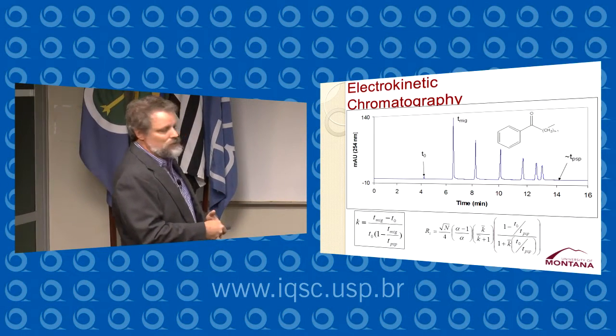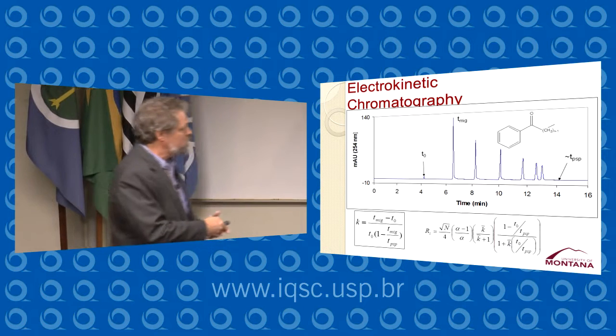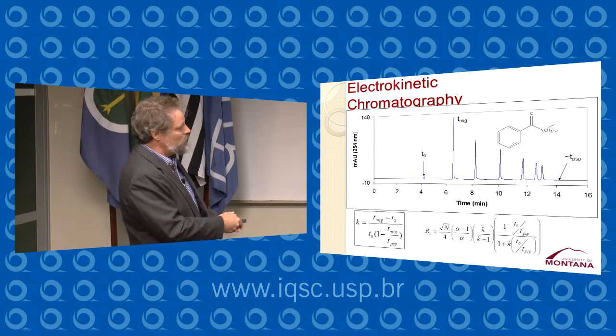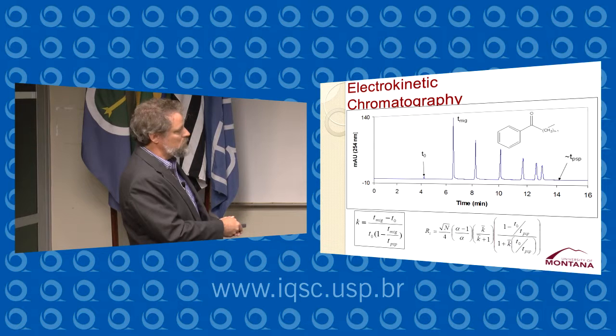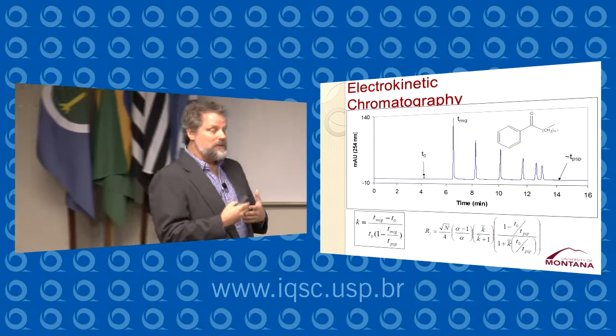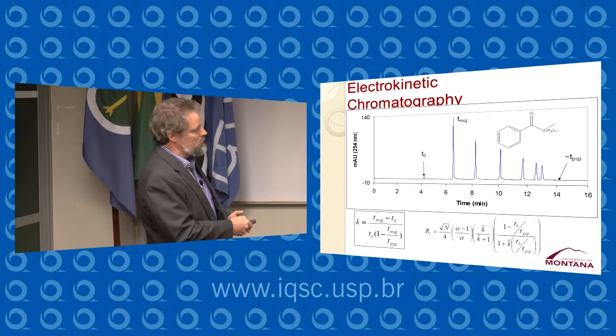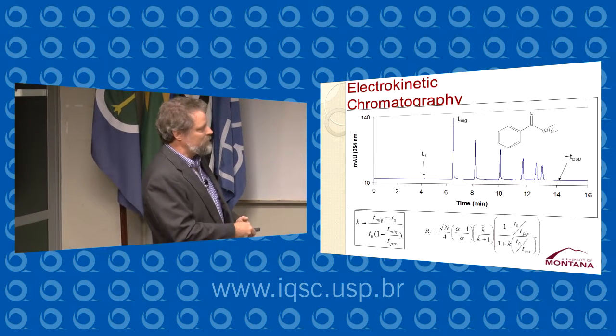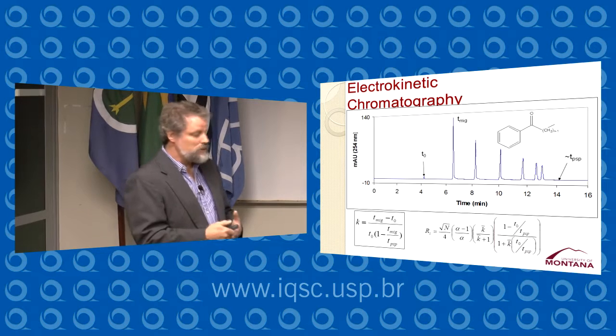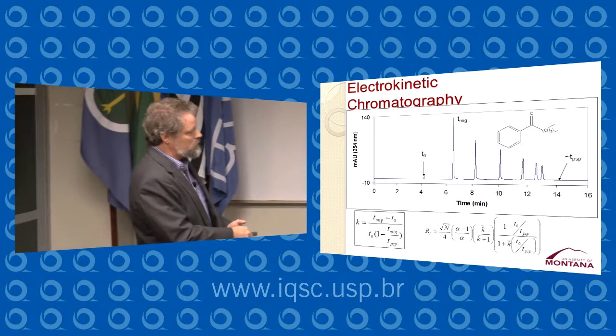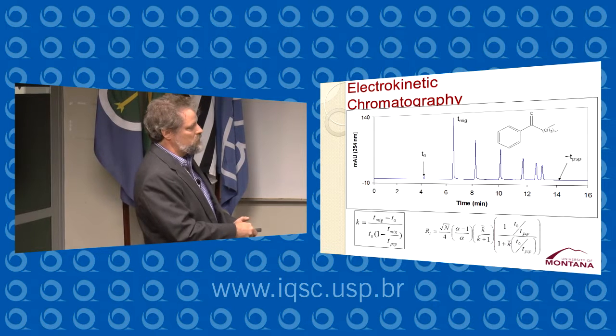So that's a significant difference between electrokinetic chromatography and conventional chromatography. We have this separation window to work with. We can calculate retention factors just like we do with conventional chromatography, but now there's a new term in the equation which accounts for the migration time of the pseudostationary phase. And we can also predict what we would expect to get for the resolution between two compounds using, again, a very similar equation to what we use in conventional chromatography, but now with an additional term which accounts for the migration time of the pseudostationary phase.